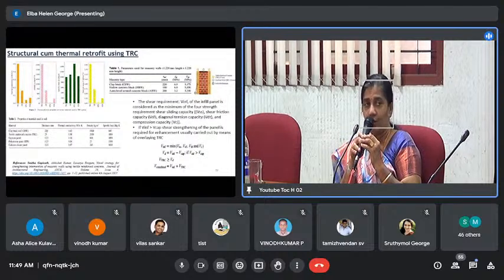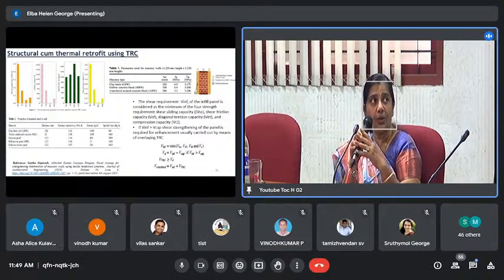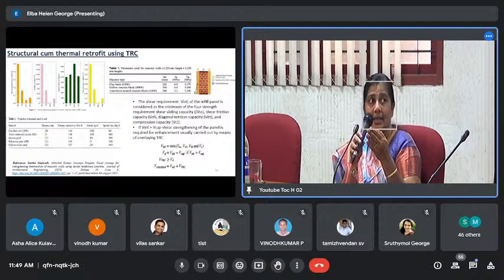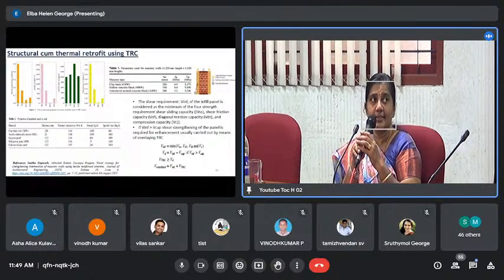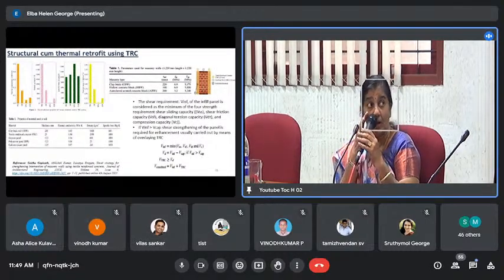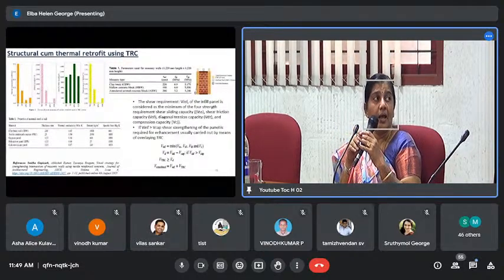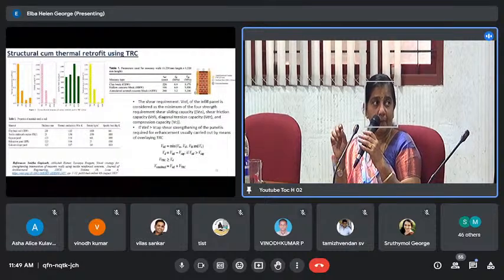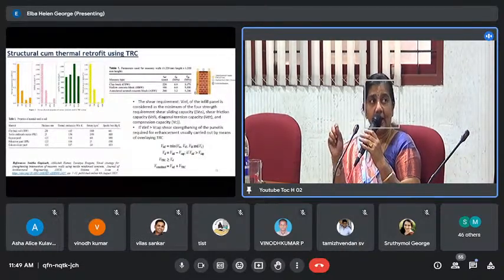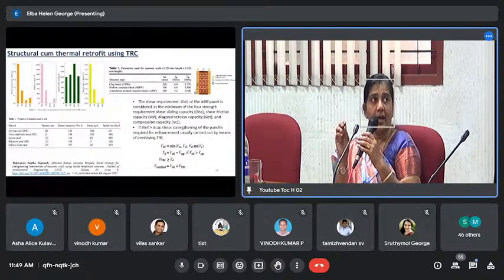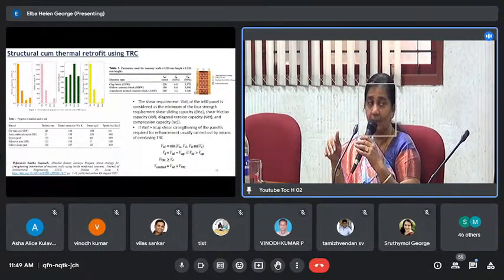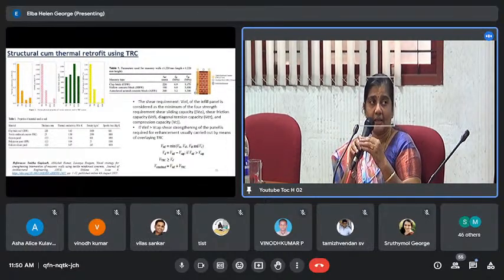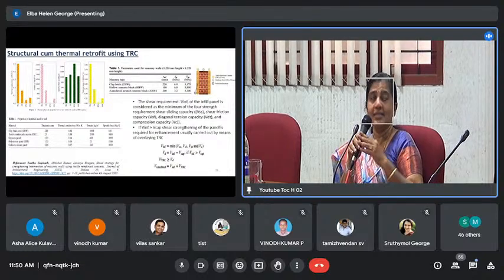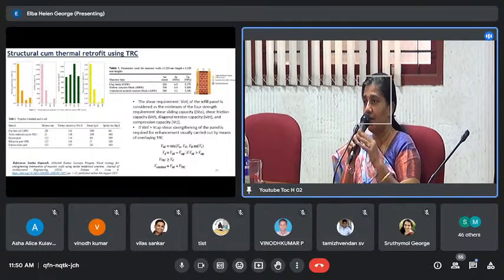Coming to structural cum thermal retrofit, it is a recent study wherein we have worked out whether TRC alone, or TRC integrated with calcium silicate or EPS, can lead to structural cum thermal retrofit possibilities. And we also tried out whether this conceptual strategy will work for clay brick walls, hollow blocks and AAC blocks. We targeted a particular enhancement in the shear capacity and a particular enhancement in the thermal characteristics, and which system should be used. We derived a methodology. That method was proven to be successful, and this is a proof of concept which tells you that it is a material which can be thought about for this structural cum thermal retrofit.